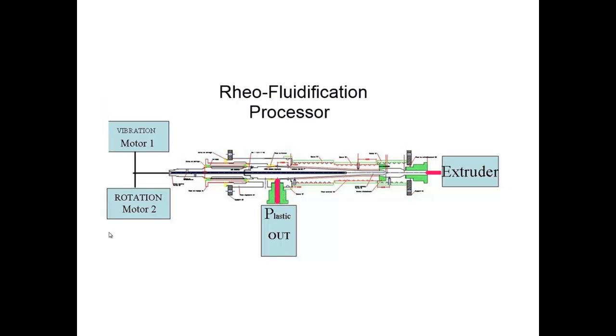So the cone which you see inside is the rotor, and it's a conic expanding the flow from the inlet to the outlet. The outlet is on the side, you see plastic out, and all the rest of the mechanics is just to make the inner rotor rotate and vibrate. The outside, the stator is cooled and heated, and so that the melt can flow through, and defines a gap which is between approximately 1 millimeter to 4 millimeter. Of course, the cone can be actually moved to increase or decrease the gap. Okay, so that's the way this thing looks.